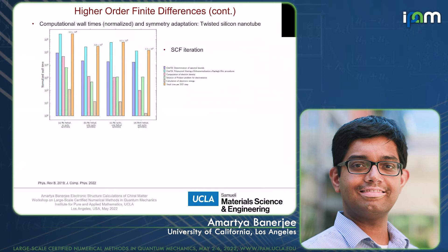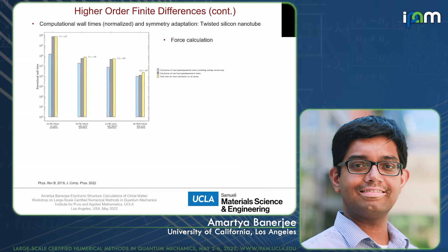Because this method intrinsically builds on symmetry, the more symmetry exploited the better it performs. Comparing wall-clock time per SCF step with no symmetry versus exploiting both cyclic and helical symmetries shows roughly a 20-fold speedup — and this is not a particularly large problem. Because the K-points are embarrassingly parallel, we can actually simulate very large tubes, including silicon nanotubes with diameters up to the micron scale.